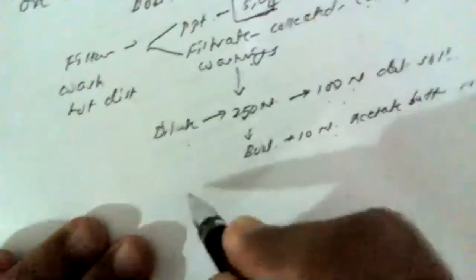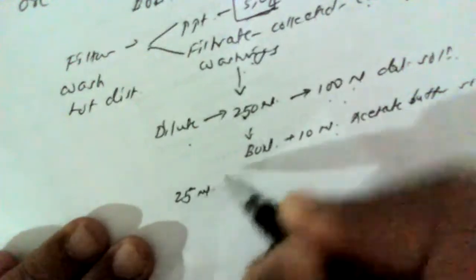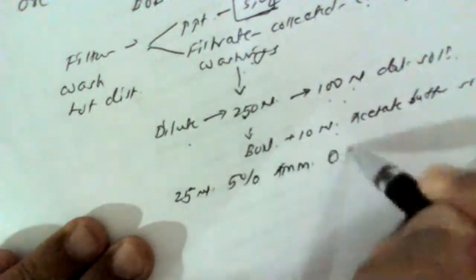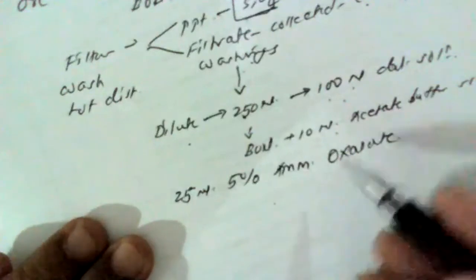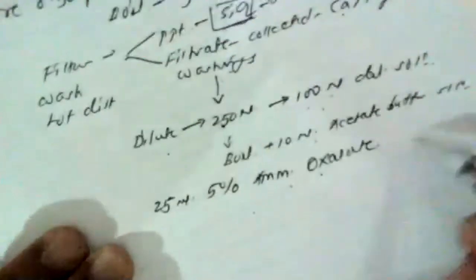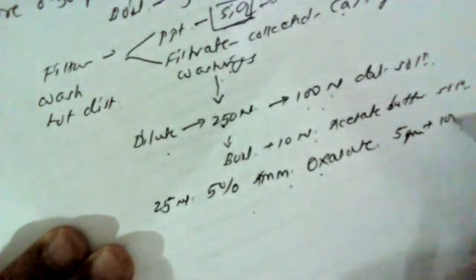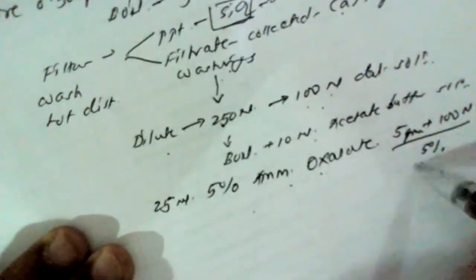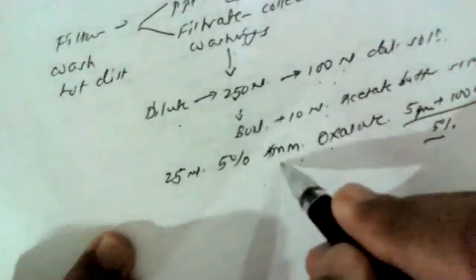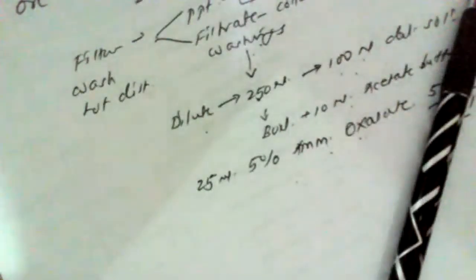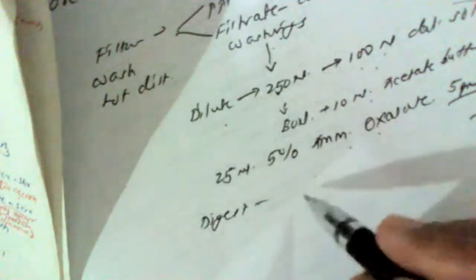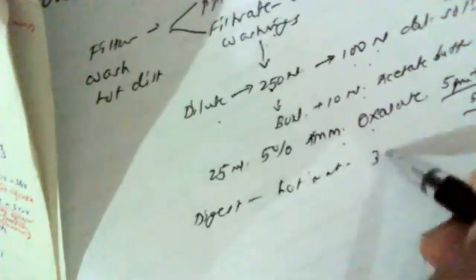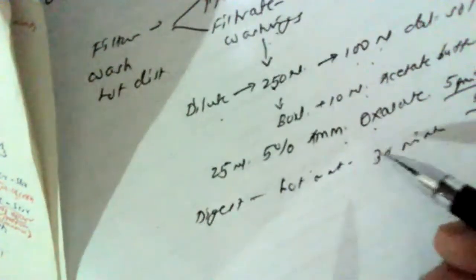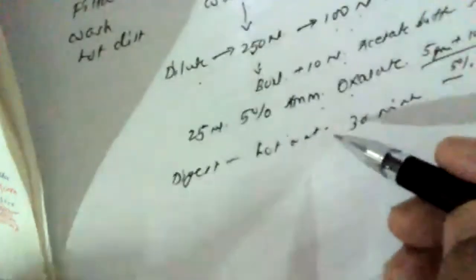Then to this boiling solution, we have to add 25 ml of 5% ammonium oxalate solution. 5% means 5 gram of ammonium oxalate solid is taken and dissolved in 100 ml distilled water, that is a 5% solution. So 25 ml of 5% ammonium oxalate solution is to be added into this solution. After adding this, we have to digest by keeping the beaker on a hot water bath for about 30 minutes. After 30 minutes or so, the supernatant liquid becomes clear and at the bottom of the beaker we can see a white colored precipitate that settles down.